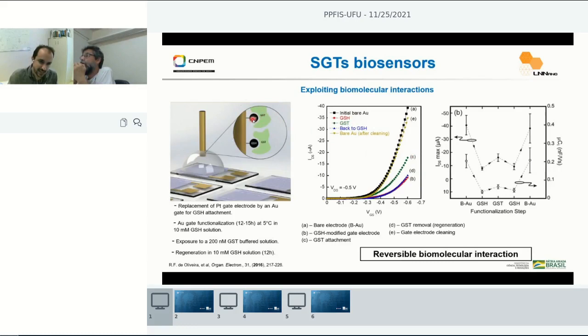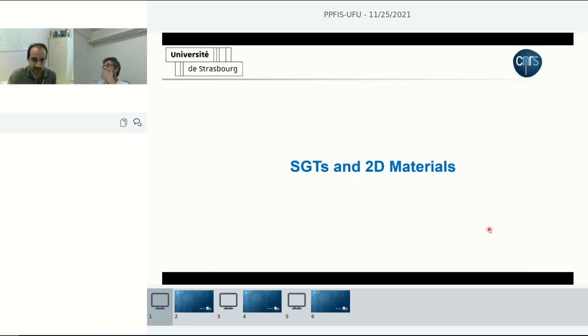If we take this modified gate electrode with bioreceptor and protein, and expose it to a very high concentration of bioreceptors in solution for eluting, to remove these, we can reversibly remove the proteins. When we do that, the current goes back to its previous state. And if we remove completely all organic matter on top of the gate electrode, we recover the initial performance. This means that we can reversibly detect biomolecular interactions. And here I show how the current changes at every step of this process of functionalization and detection, and also the product of carrier mobility times interface capacitance.